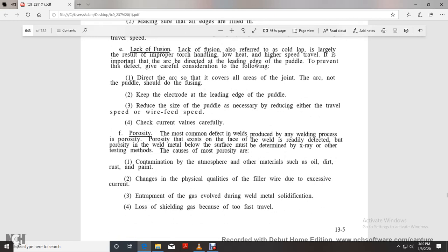Porosity. The most common defect of the weld, produced in any of the welding processes, is porosity. Porosity that exists on the face of the weld is readily detected, but porosity below the surface of the weld must be determined by X-ray or other testing methods. Causes of porosity include contamination of the atmosphere, other materials such as oil, dirt, rust, and paint that change the physical qualities of the filler wire, excessive current, entrapment of the gas evolved during weld metal solidification.